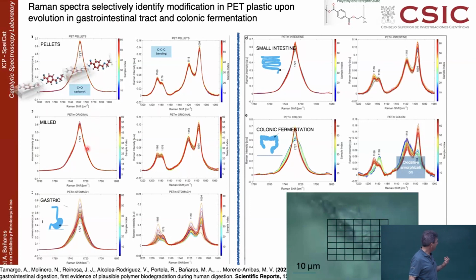And after it goes into the stomach, into the small intestine, and into the colonic fermentation, you will see how at different positions you start to see some changes. You see that already in the gastric, you see some changes between the 60 spectra. Some of them look different. Also here, you have some changes in the relative intensity of those ones. So this is telling you that the plastic is changing in a not very homogeneous way, but you can see that here, it is no longer the same. There is a progressive degradation of the plastic already in the stomach.